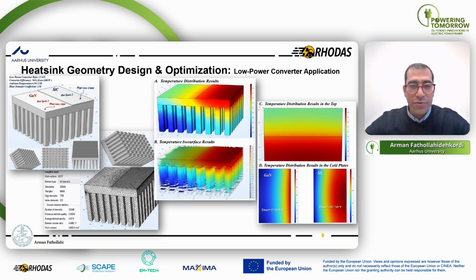If you want to optimize something in COMSOL, it will be very time-consuming because of each iteration. For the air-cooled thermal management system, it takes something like 1 hour, 2 hours for each iteration and each simulation. But sometimes in the liquid-cooled, it takes 8 hours, 9 hours. So if you want to use a normal iteration-based optimization algorithm, it's more or less impossible, because you need to run different simulations up to 1,000 iterations, 500 iterations, and with the capacity we have and with the time that we have in the applied project and ITRL project, it's impossible.